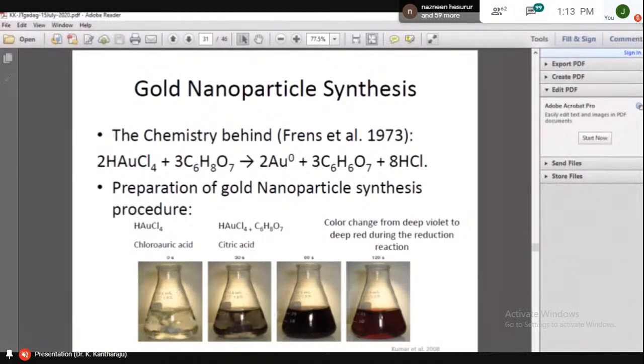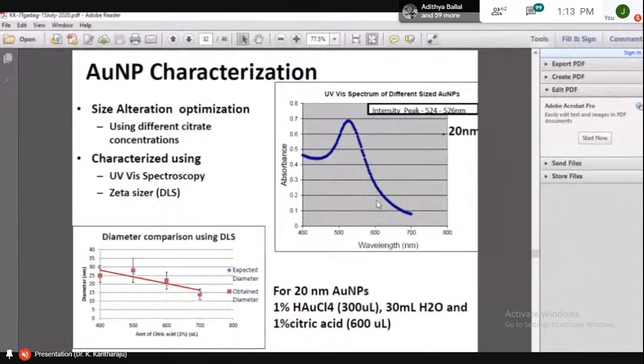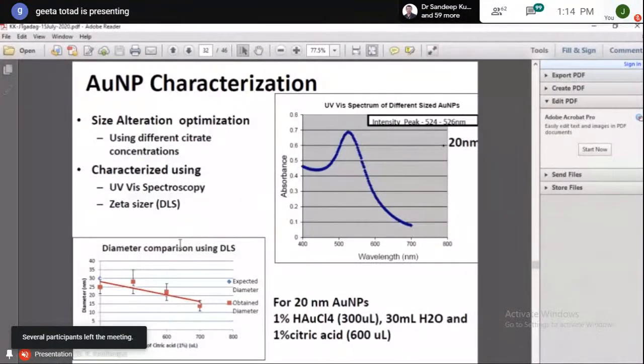You can see it by the color within 2 to 3 minutes: you are going to see a very beautiful dark red color. This is the indication. Then it is examined through UV absorption, and everything is available in the literature. The beauty of selecting citric acid is that by varying its concentration, you can get different sizes of gold nanoparticles. That is what we wanted, because we want to make them as small as possible, since they have to penetrate in both in vitro and in vivo studies. That is our aim: when you take a virus and put it over a nanoparticle, that has to be